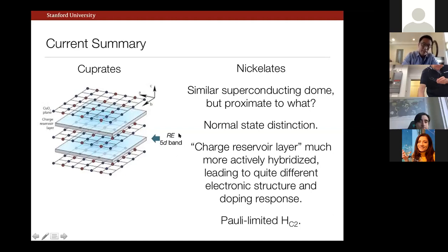What is pretty clear from all of the theoretical work in this field is that the rare earth states in our charge reservoir layer have a much more active role, namely that they are hybridized such that they contribute band states in the vicinity of the chemical potential. So that's quite qualitatively distinct. But then we also should consider that the doping of these states is again a complicated theoretical question, difficult to address. If I'm worrying about band states arising from, let's say, the neodymium in this layer, as we non-trivially substitutionally dope with strontium, the overdoped side of our dome, if you want to call it that, is 25% substitutional doping. This is very heavy disorder. This becomes more like a random alloy type of situation, and how we think about that is an open conceptual question. But certainly it's one of the things we're worrying about in terms of why we don't see a good metallic overdoped regime.